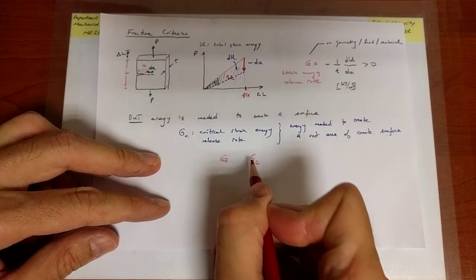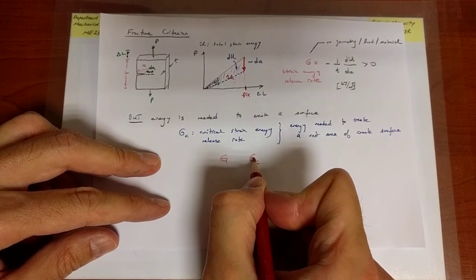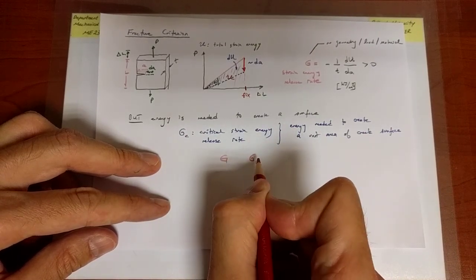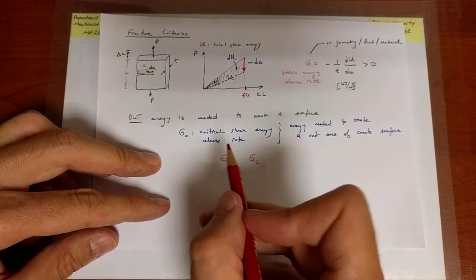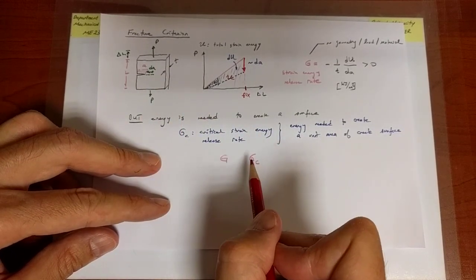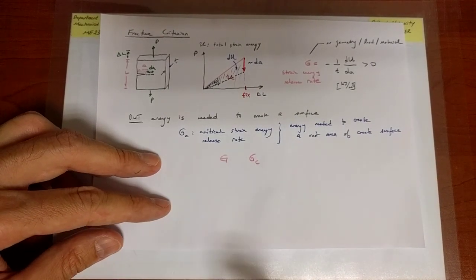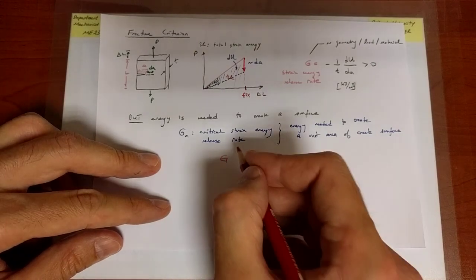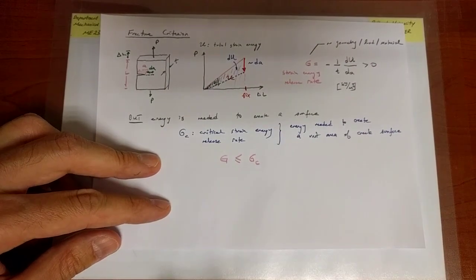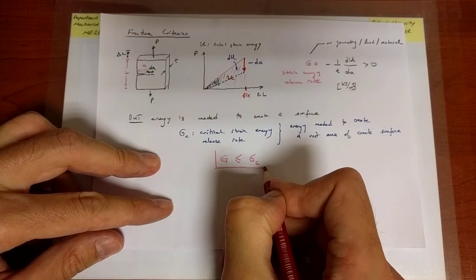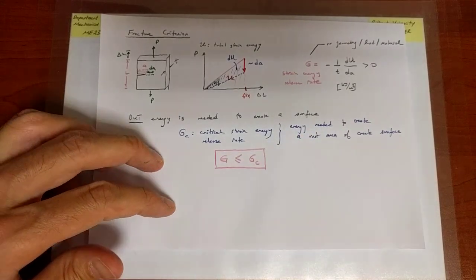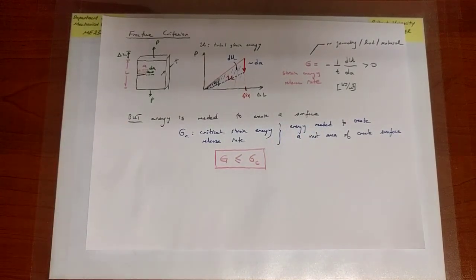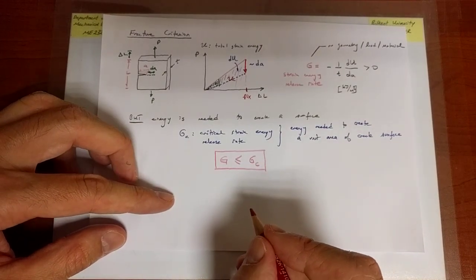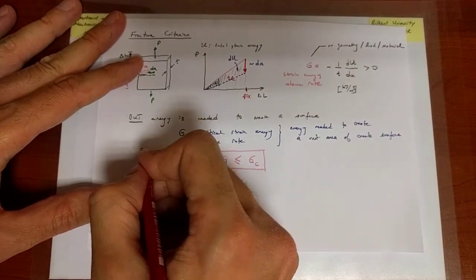So if the value of G is less than GC, the crack will not propagate. As soon as it is equal to GC, it's in the process of propagating. If you make a design in which you find that for a given load G is larger than GC, that means the crack will immediately propagate and fracture the system. Okay, so I will write my criterion as I've done earlier. If G is less than GC, it will not propagate. If it's equal, it's in the process of propagating, and it can never actually physically be larger than GC, at least not in the context that we are discussing. So this is called the Griffith criterion.